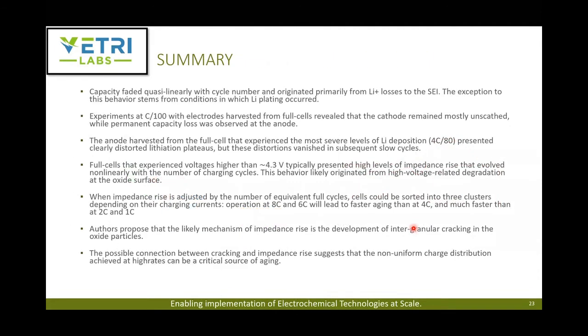So in summary, the capacity faded quasi-linearly or non-linearly with cycle number, and it primarily originated from lithium ion losses to the solid electrolyte interface, the SEI. The exception to this was when lithium plating occurred. That can be considered as an additional inventory loss in addition to the SEI. In the experiments with C over 100, the full cell's cathode, as we just saw, remained mostly not impacted in capacity, but the anode capacity was impacted. But in the case of impedance, it was the cathode side, based on their reference electrode studies. They comment on that later.